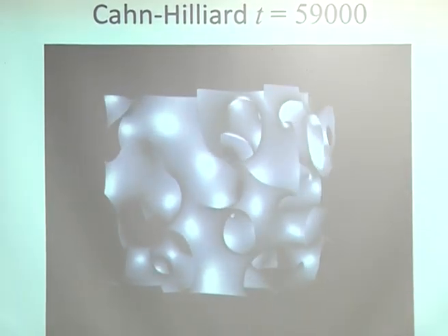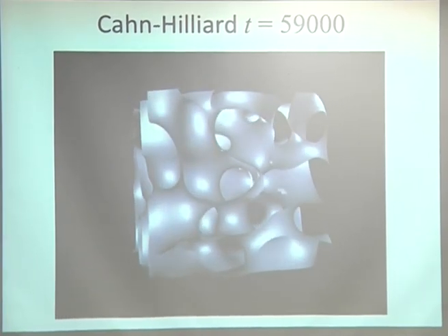That's the picture that you see here. And so in 3 dimensions, you get structures that look like this. So it's highly interconnected. It's called bicontinuous. You can move from one end of the structure to another and never leave one phase. And it's very, very topologically complicated.